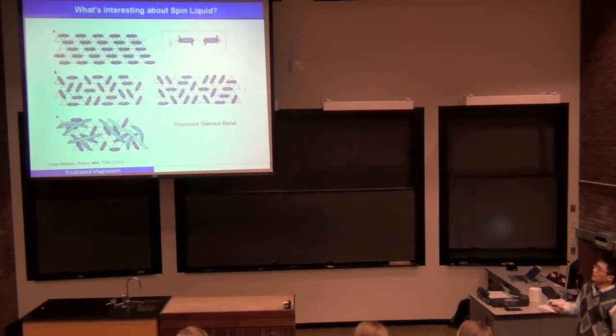And instead of a classical Ising type of spin, if we bring in a more quantum mechanical spin, for example spin 1/2, and instead of nearest neighbor Ising type of spin, we have Heisenberg type of spin, which is isotropic in space, then it is possible to have spin singlets forming at nearest neighbor pairs. So here, instead of one spin pointing up and another pointing down, the spins on the nearest neighboring sites can form a singlet, which is a superposition of up-down and down-up configurations. And when this happens, we can have either this well-formed lattice order of spin singlets, or we can have a more exotic order, which is called the resonating valence bond, where the state is actually a superposition of all possible ways of mapping the lattice with these singlet states.